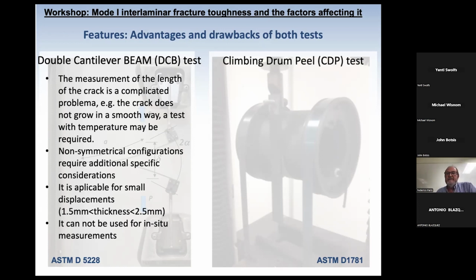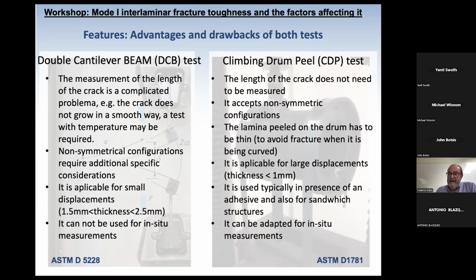On the contrary, the CDP test presents another set of features. The length of the crack does not need to be measured. Well, first of all, I have to say that this test is typically used, or has been used, for sandwich structures and in most cases in the presence of an adhesive. Clearly this accepts non-symmetric configurations, and in fact the lamina peeled on the drum has to be very thin to avoid fracture when it is being curved. It is applicable for large displacement, no problem with this. And the most important thing, in my opinion, is that it can be adapted for in-situ measurements.